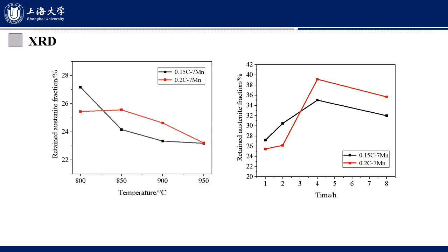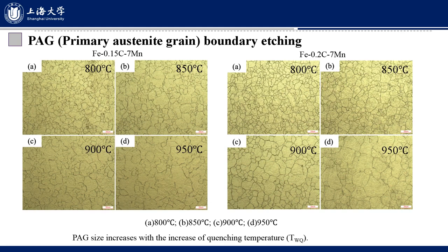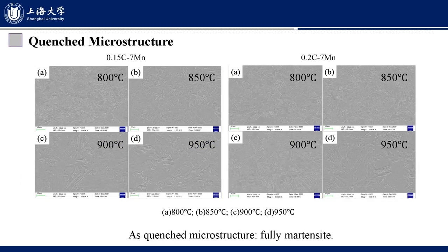Retained austenite fraction changes with the water quenching temperature. It decreases with water quenching temperature increasing. And retained austenite fraction increases first with the intercritical annealing time, and finally decreases. Primary austenite grain size is shown in this figure. It is clear that lower water quenching temperature is beneficial for the refinement of the original microstructure of the steel. And the quenched microstructures for all these different water quenching temperature conditions are fully martensite.